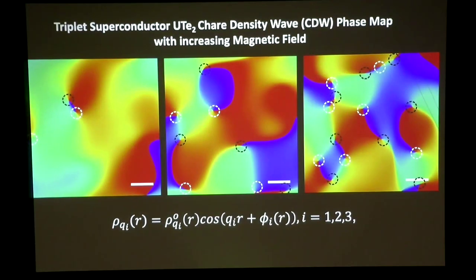OK, so finally, there's one last thing I want to show you that we can measure with STM. You can not only get amplitude information from the Fourier transforms, but you can also get phase information. And this is really interesting. This is phase information extracted from the same kinds of maps, dI/dV maps and Fourier transforms, that I just showed you. What this is showing you is the phase of a charge density wave. So this should be charge, I'm sorry about that.